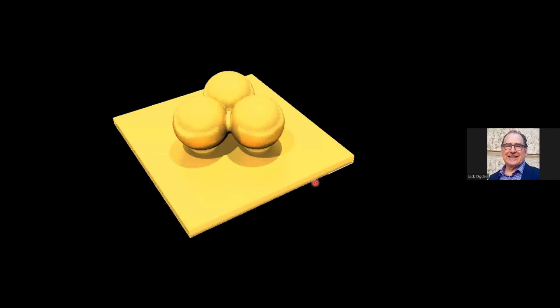Now, the wonderful thing about this kind of soldering is that you can carry on doing it on the same object. With modern solders, if you buy what we call a solder alloy and make jewellery, if you solder a ring or solder a joint on something, you can't then use the same solder again on the same piece because it raises up the temperature. So soldering the second joint will make the first joint melt again. But with this copper salt soldering, you can carry on doing this over and over again on the same piece. Each time you solder it, it just gets, if you like, even more firmly attached. So you can build things up using this technique.